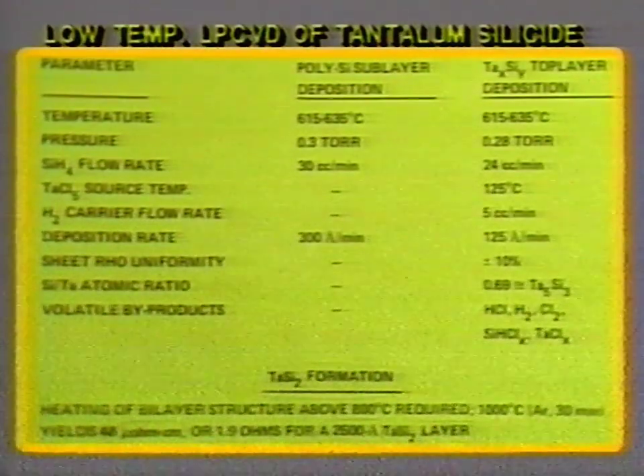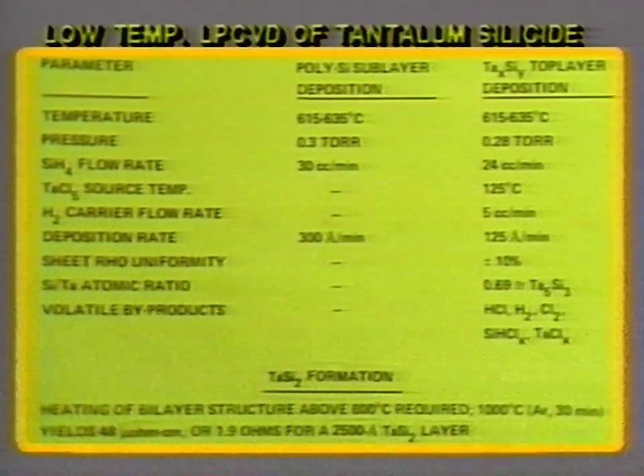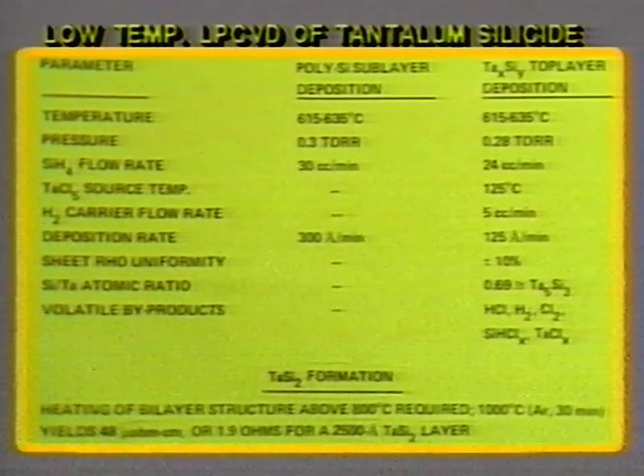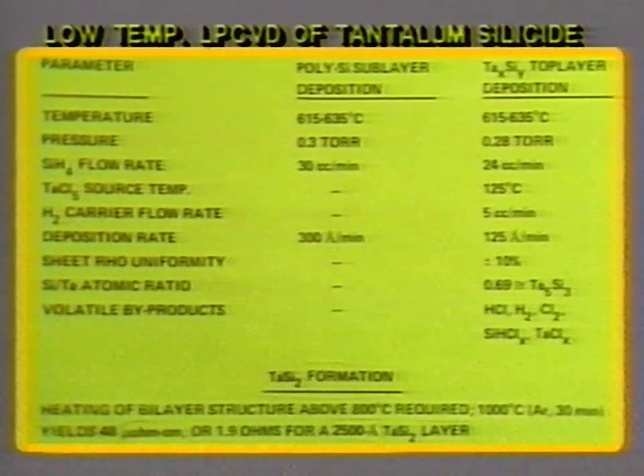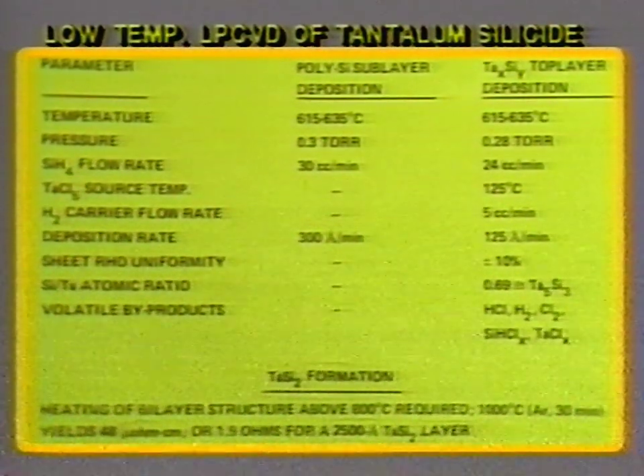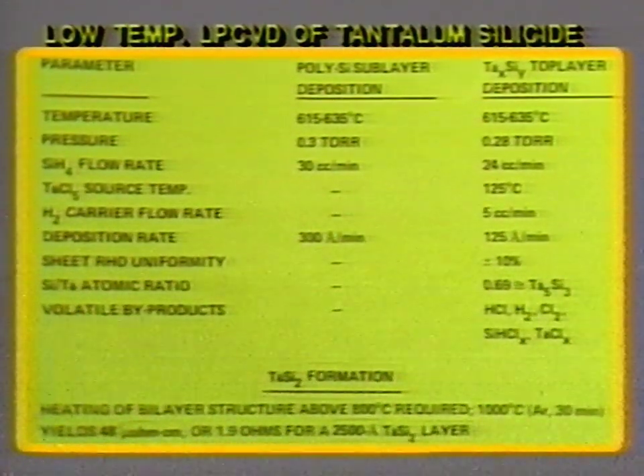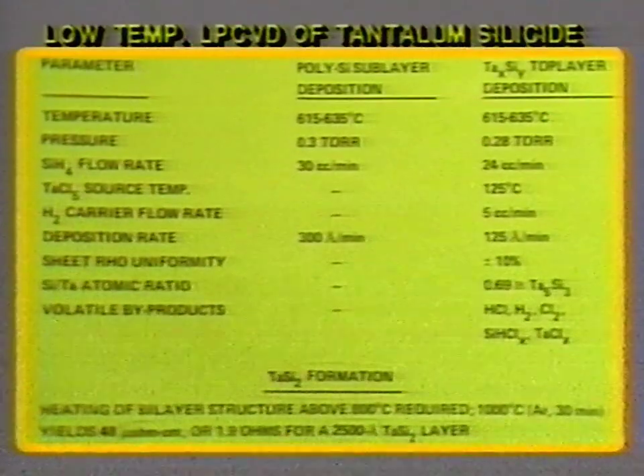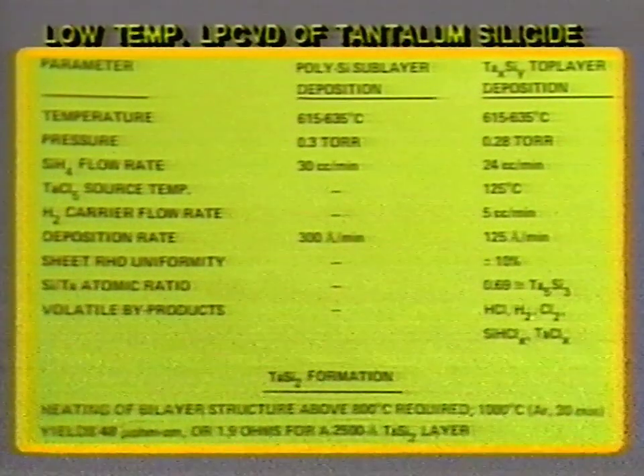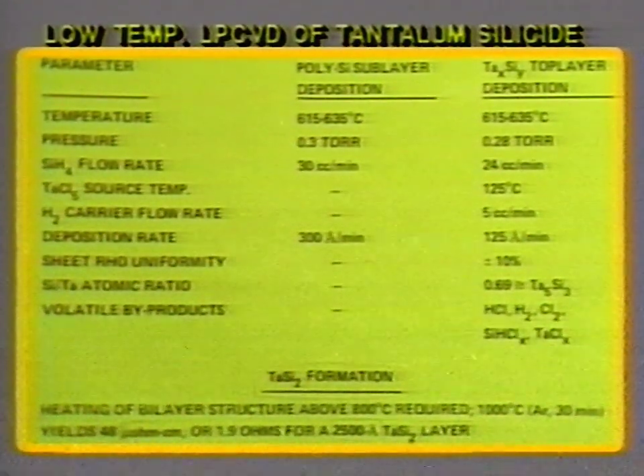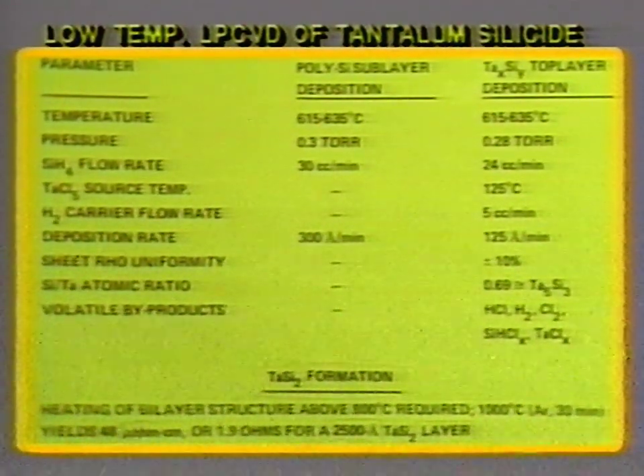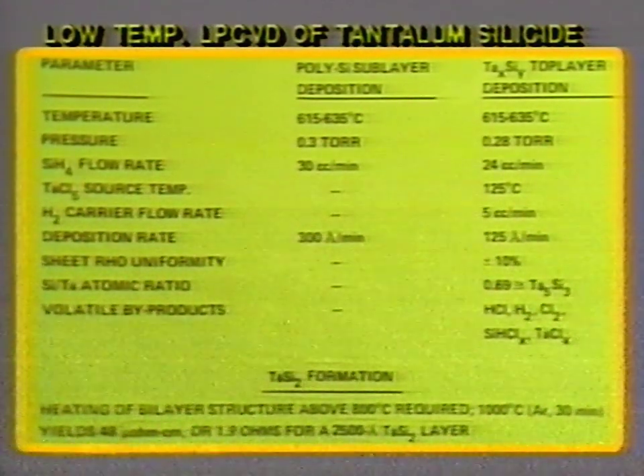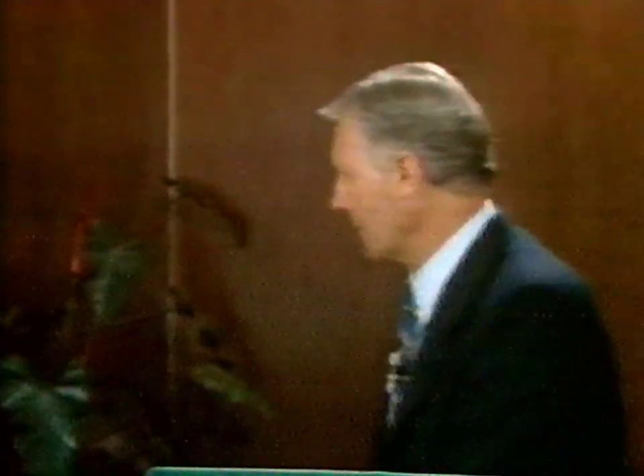But if we give a thermal annealing treatment to the final structure, we can obtain exactly what we like, namely a stoichiometric film of tantalum disilicide, which has the best conductivity, of course, and that's the kind of film we want. However, we do have to heat to a temperature of 1,000 degrees C in argon for, say, 30 minutes in order to obtain a 48 microohm-centimeter type film. Nevertheless, the attractive feature of this type of process is that it can be done in the same reactor under very similar conditions, just by adding one additional component, namely the tantalum pentachloride, to the silane mixture.